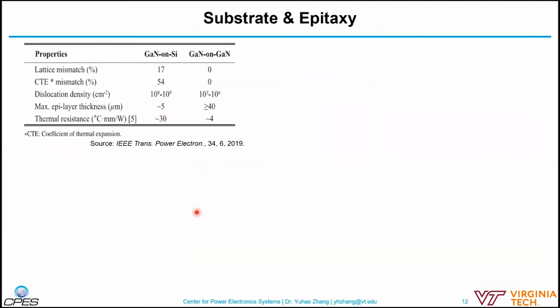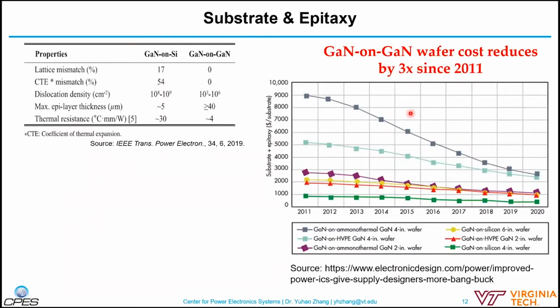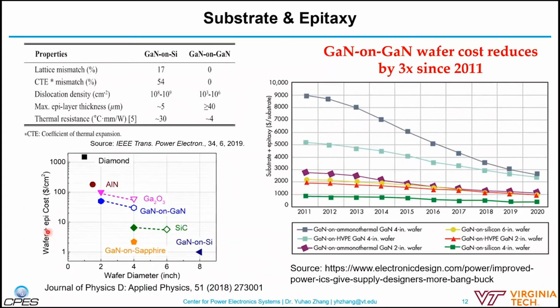Okay. So when we talk about vertical GaN, the popular substrate and epi will be on a freestanding gallium nitride substrate. That will be different from the GaN on silicon that is used in today's commercial lateral GaN HEMTs. Of course, if we have these freestanding materials with a zero lattice mismatch and very low dislocation density, there are a lot of benefits. And the price we pay for this better material property is the cost. Over the last several years, the cost of the GaN wafer has already been reduced quite a lot. But if we look at the wafer and epi cost per area, it's still two or three times higher than that of silicon carbide, and of course much higher than lateral GaN on silicon.